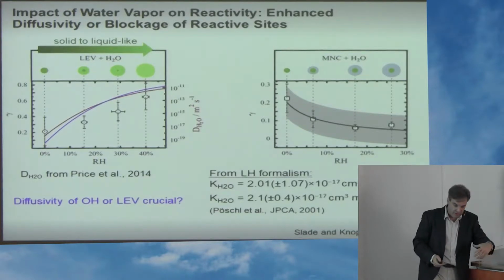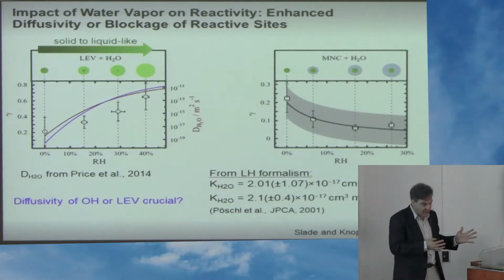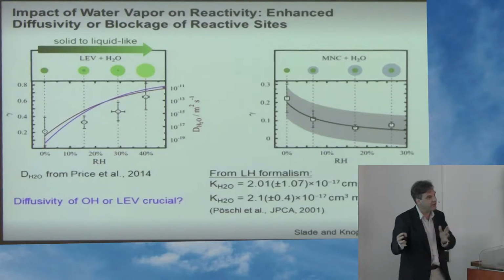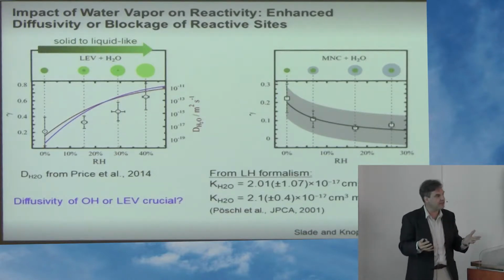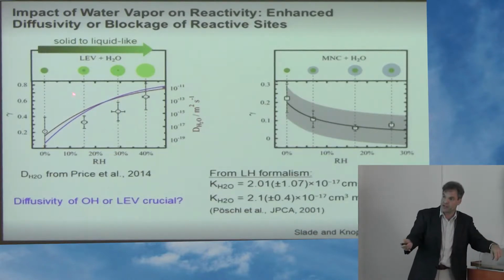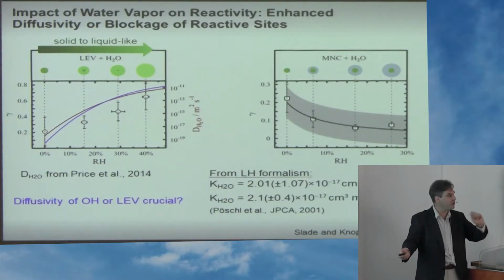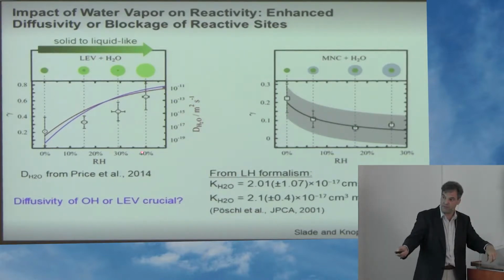We were then interested — okay, we know the organic changes phase, so how does a phase change affect this kinetics? We used aerosol particles in this experiment and measured the reactive uptake coefficient for levoglucosan as a biomass burning surrogate material, under dry conditions. It's solid, glassy, and the reactivity is about 0.2 — so 2 out of 10 OH reacts. Then we humidified them up to 40%.